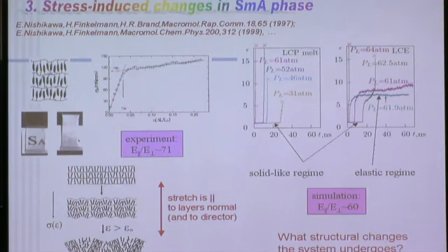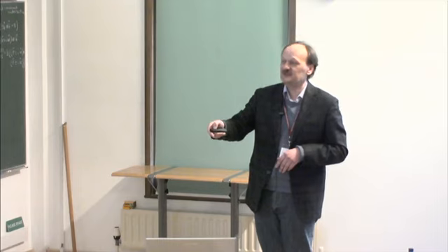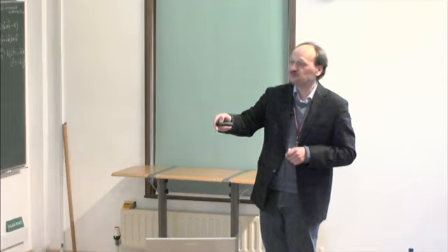Now again, if we stretch the smectic elastomer in this direction, we have quite the opposite situation. Here the sample shrinks and it becomes turbid. So it was suggested in those papers that smectic layer undulation is taking place here, and that's why we have a non-transparent sample.